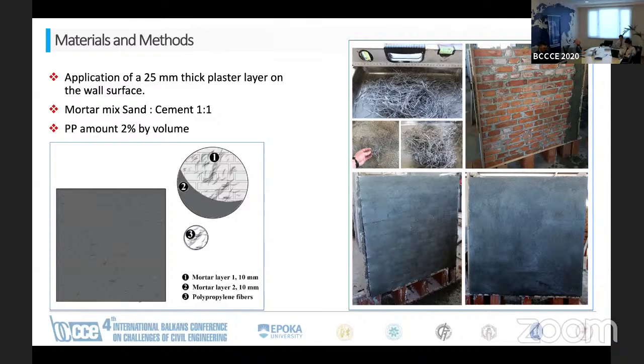The composition of mortar is a mix of just cement and sand. We started with a ratio of 1:1. We have also done some other tests in a ratio of 1:4, so 1 portion of cement and 4 portions of sand. And the polypropylene fiber amount is around 2% in volume.